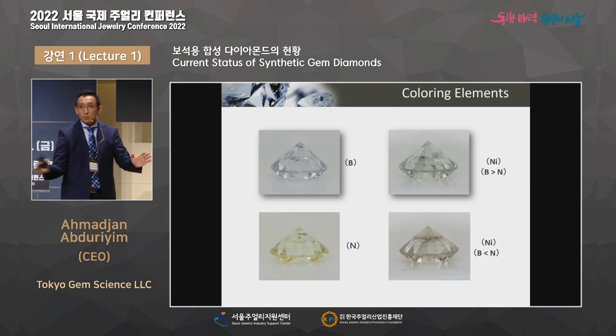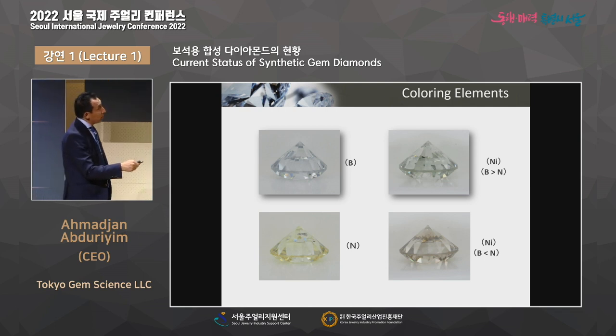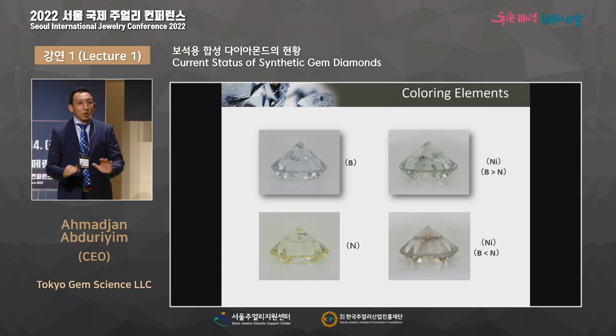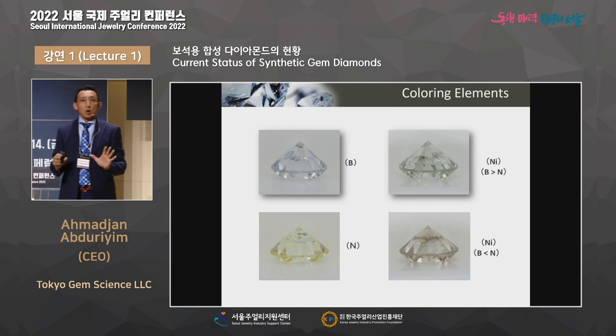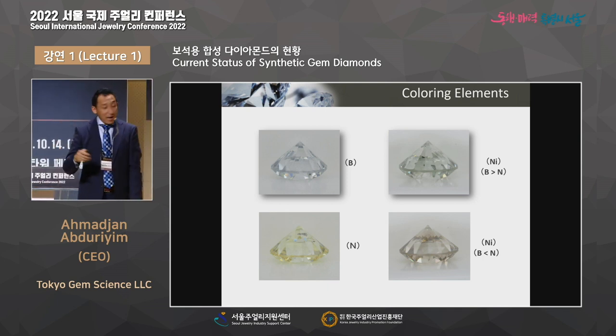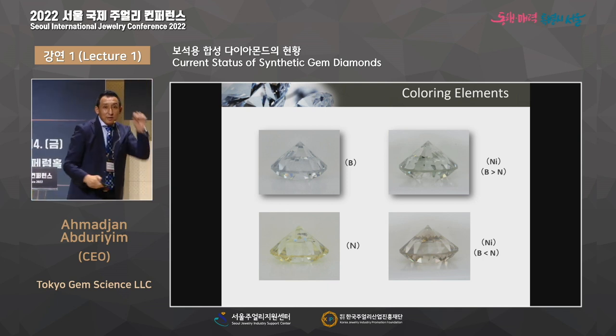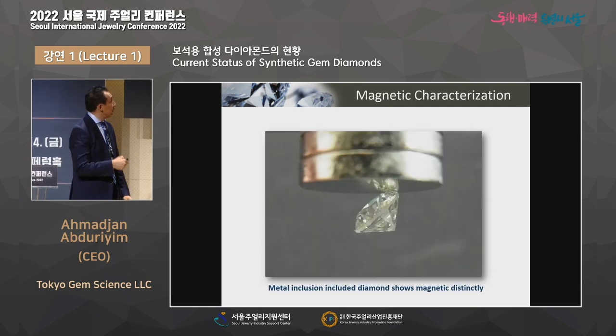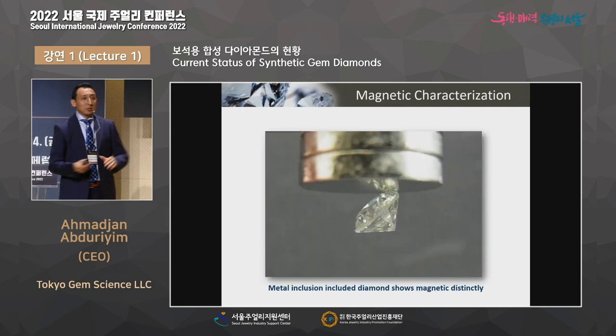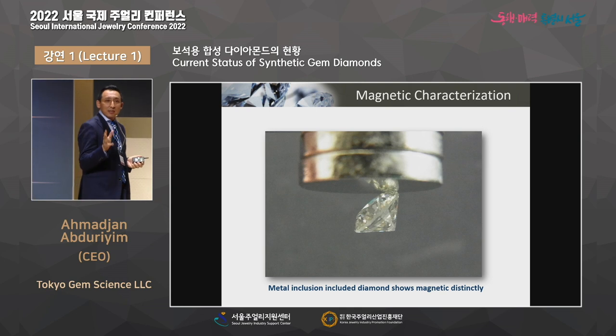This nickel is from the same metal flux. However, when boron is more than nitrogen, it is going to show this greenish color. If the boron is less than nitrogen, it shows brownish. So normally when you see the Chinese synthetic diamond, you see the colorless and this kind of very tint color. And sure, this is what we study, this synthetic diamond.